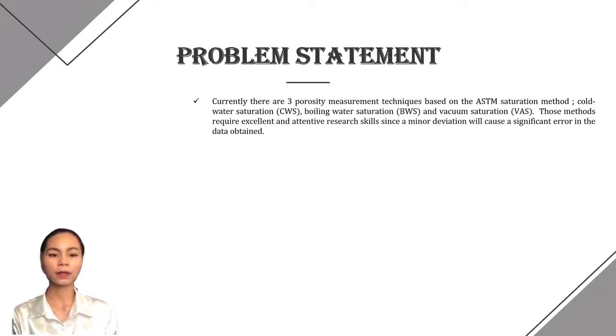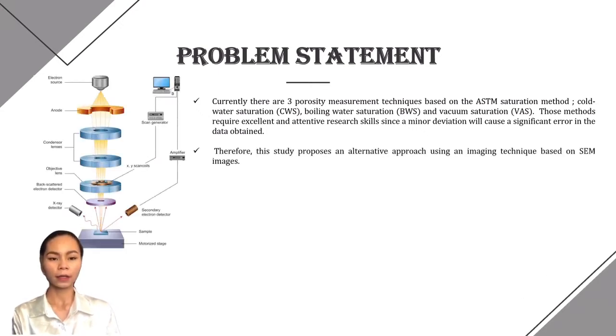This study is to be done because currently there are three porosity measurement techniques based on the ASTM saturation method, namely cold water saturation, boiling water saturation, and vacuum saturation. However, those methods require excellent and attentive research skill because they will cause significant error in data if not done properly. Therefore, this study proposes an alternative approach using an imaging technique based on SEM images.